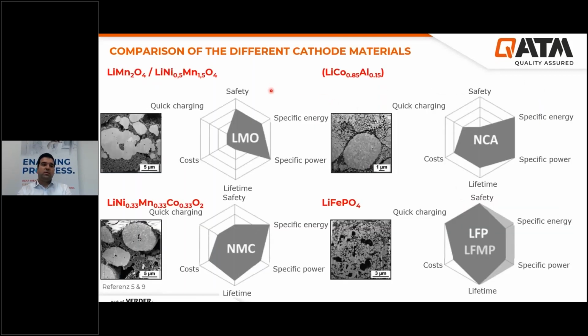Now I want to make a comparison between the different cathode materials. For example, here we have lithium manganese oxide or lithium nickel manganese oxide. In these materials, we have a very good specific power, but the cost is not appropriate. It's very high. In lithium nickel manganese cobalt oxides, we have a very good specific energy, good lifetime, low cost, but the charging is not so quick. In lithium cobalt aluminum, the safety is very low.